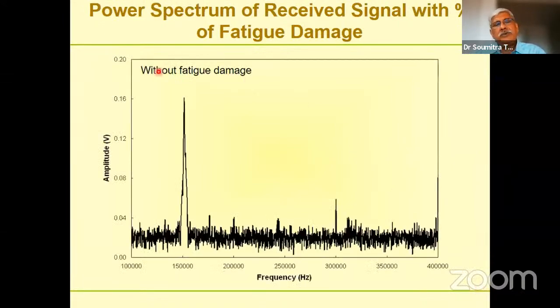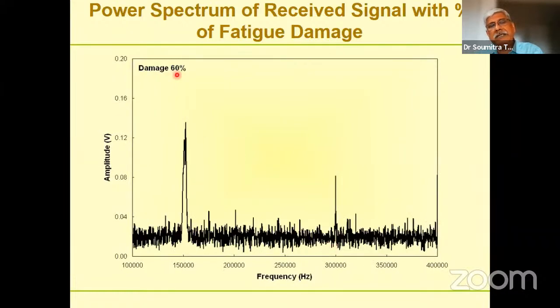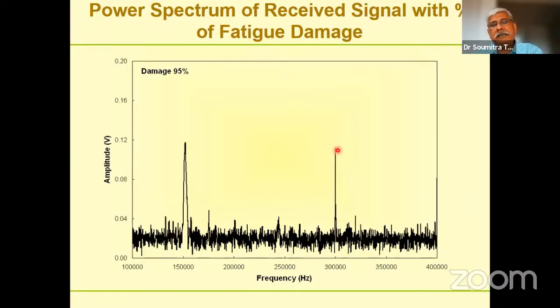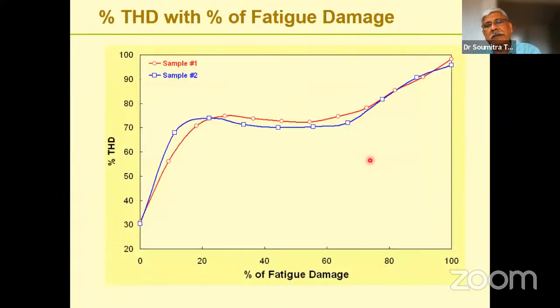See, when the material was without any fatigue damage, virgin, without any tests, we find that this is the primary signal that we were putting in, and there is a harmonic, because any material will have some dislocations, will have some damage already in it, a very small harmonic. But as we fatigue it, and when the damage is 60%, look at the increase in the second harmonic. When the damage is 95%, the increase in the second harmonic is much more than that. So at least you can tell by a study of the second harmonic from nonlinear ultrasonic how much amount of damage has taken place.